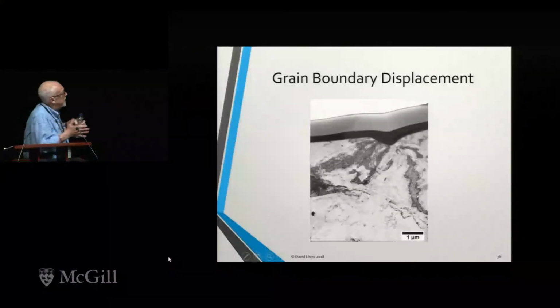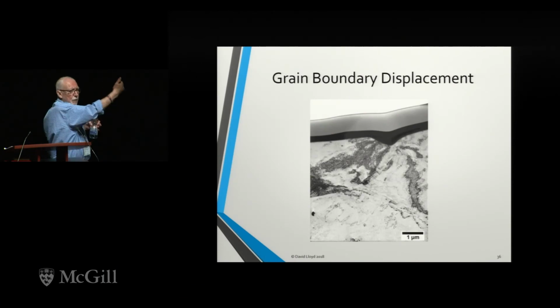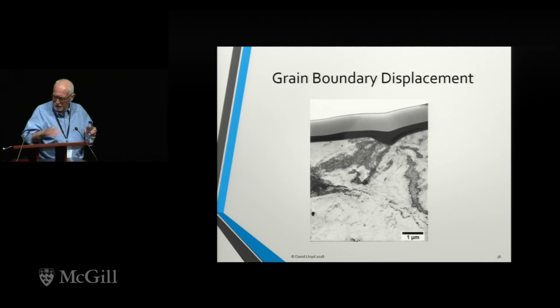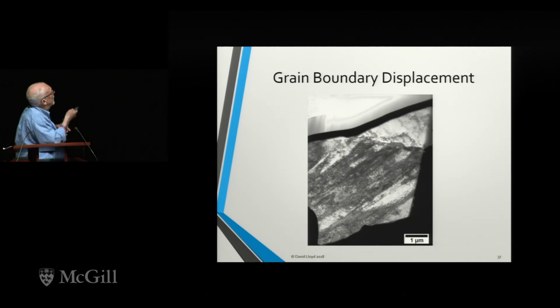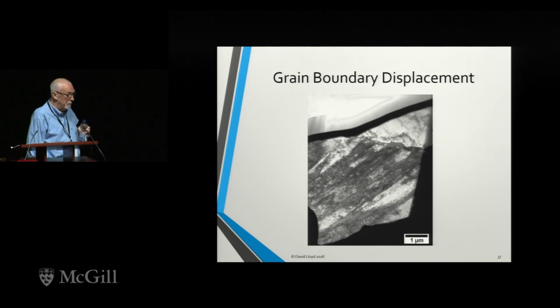You can then take a bend sample and you can use a FIB to erode out a thin foil that's including the bend surface. And that's, what do you do with my pointer, love? Yeah. So that's what we're looking at here. This is the bend surface, grain boundaries here, and here you can see the displacement that you've got associated with it. And those sorts of experiments are really very interesting. This is 6111, and again, there's that bend surface and the displacement that you've got and how that plasticity goes on. These are not trivial strains. I mean, you can get grain boundary strains in 6111 that are 0.9. So these are not trivial strains, but it's a very useful tool to look at things like damage and fracture, basically by using the bend test as a means to look at these features.